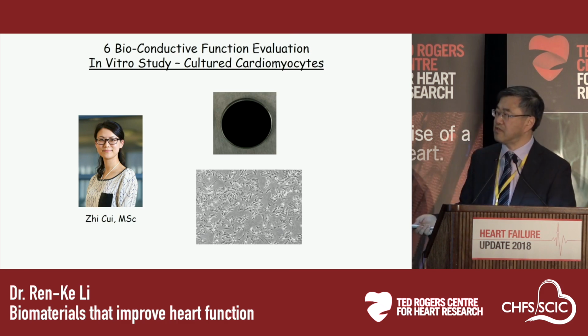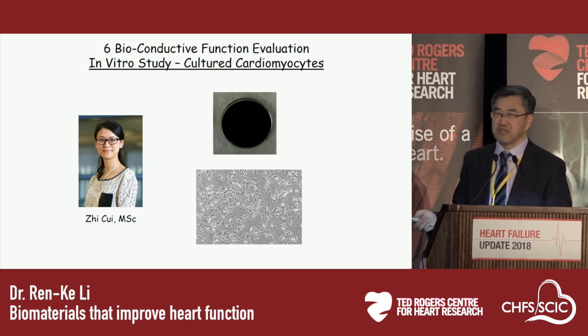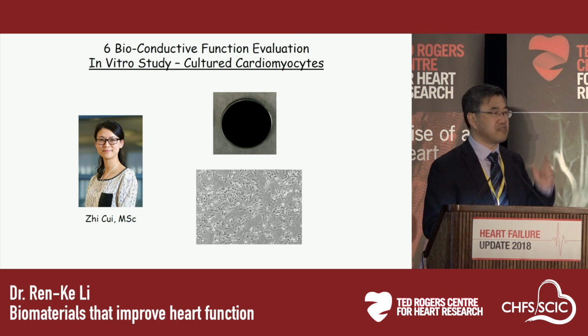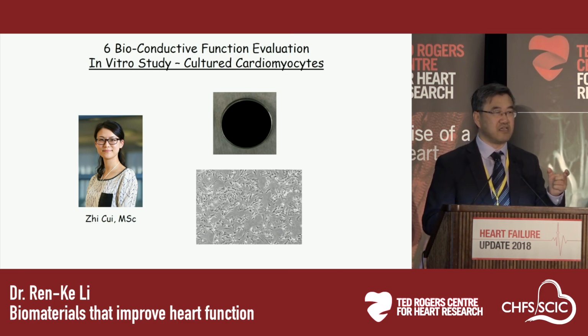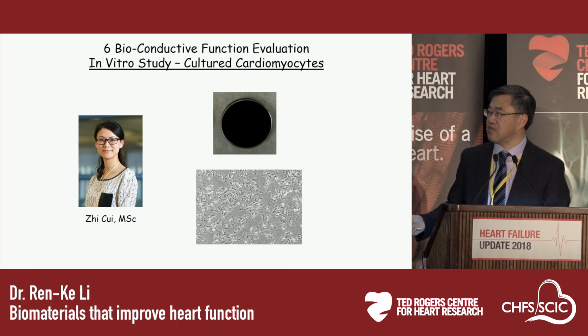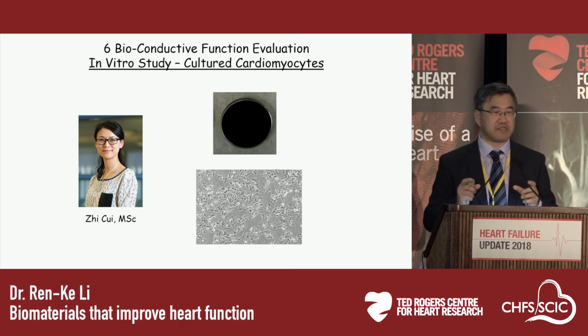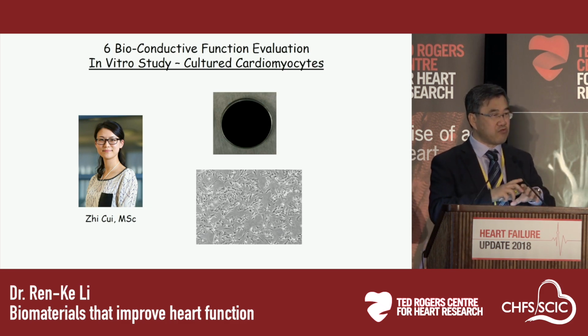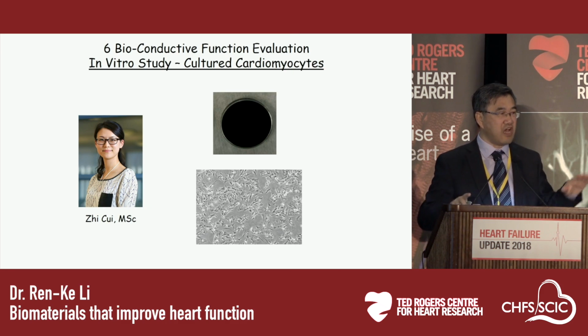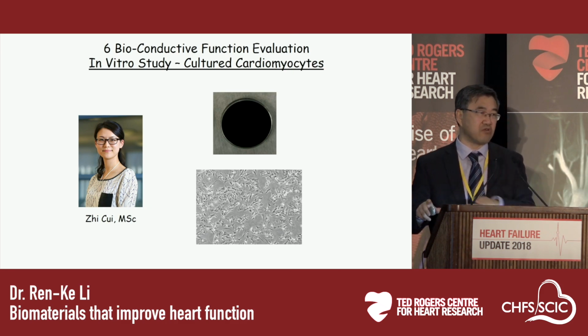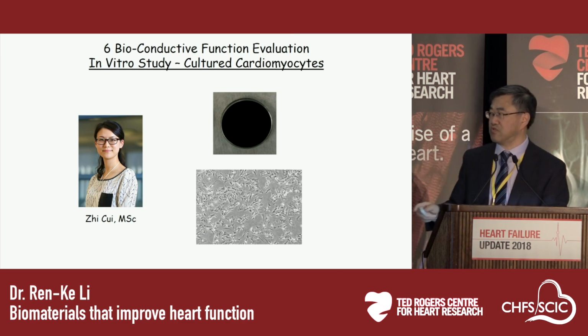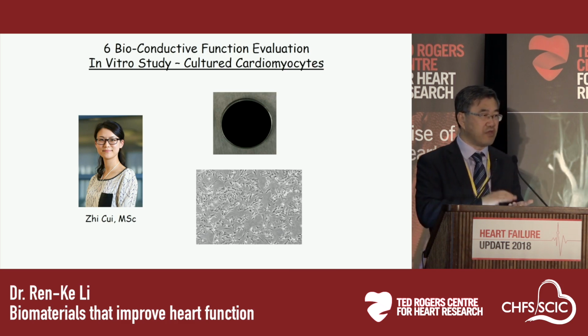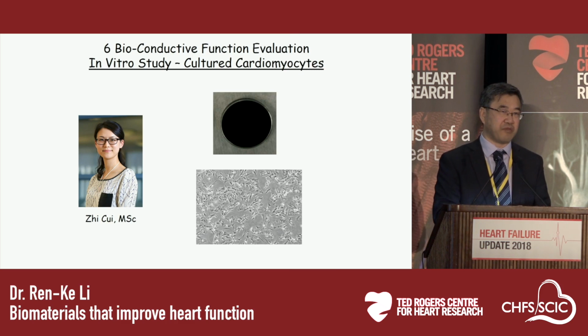On purpose, she seeded neonatal cardiomyocytes at a very low density. The reason for that is we create gaps between the cells. If we grow the cells in sheets, the conductive velocity will be very fast, very smooth, and you will not know the contribution of the bottom part, the conductive biomaterial.